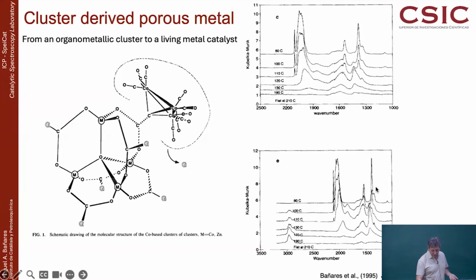Basically what happened is that at the beginning you got the organometallic cluster with the carboxylic group, the carbonyl ligands, and whatever. And as you increase temperature, you see how the material is decomposing, all the bands of the carbonyl and carboxylic groups are disappearing, and interestingly, the infrared bands of the carbonyl groups start to evolve into something different, which is the infrared band of adsorbed carbon monoxide. So the carbonyl ligand on an organometallic compound all of a sudden starts to look like CO chemisorbed on a metal. So you see the birth of a catalyst and the death of an